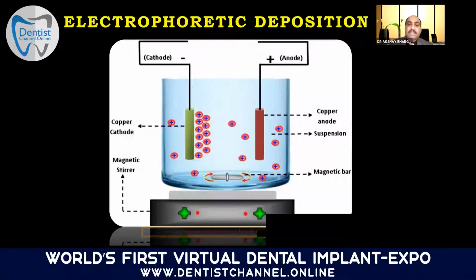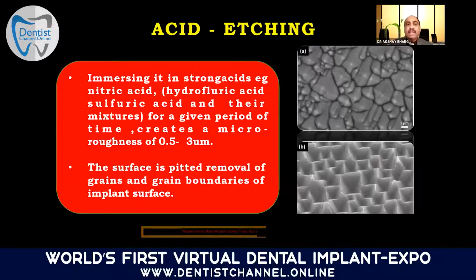In electrophoretic deposition, you have a cell where you put an anode and a cathode. I won't go more into it, and a deposition takes place. Acid etching is most commonly used, SLA, acid etching, and treatment with sandblasting. So immersing it in strong acids, that is nitric acid, hydrofluoric acid, etc., or the mixtures, where a micro thickness of 0.5 to 3 microns is created.